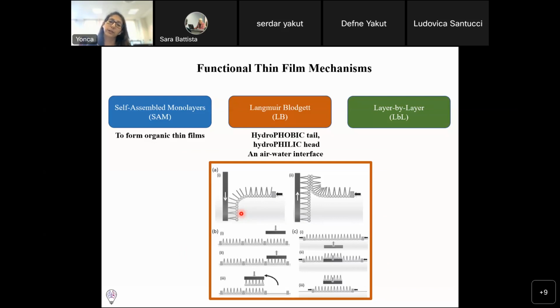So what they do is they dissolve the amphiphilic molecule first in an organic volatile solvent, and then they gently put it on the aqueous subphase. And then with the help of a Langmuir trough, it's possible to transfer the monolayer to a solid substrate. Once you have this layer transferred to the solid substrate, you can have a Langmuir-Blodgett film. But here the crucial thing is you need to have hydrophobic and hydrophilic interactions. So this is the most important part, either with the substrate surface, with the molecule, or vice versa.